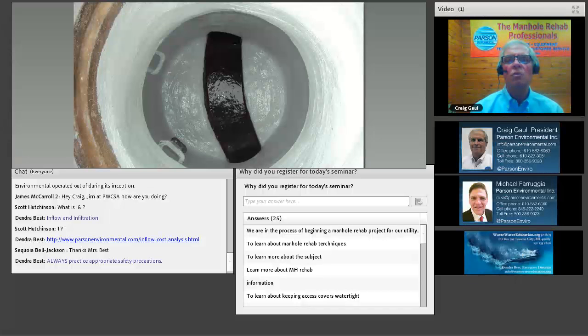The newest product on the line, and there are a few companies that have them now, is called a geopolymer material. It looks just like a cement product. It acts like a cement product. It smells like a cement product. But actually, the main ingredient, which in the MH Liner's case is Portland cement, is replaced with fly ash. And it's been found that fly ash really provides some great corrosion protection, because it takes the cement matrix out of that complete formula, and the cement is what gets attacked by hydrogen sulfide and MIC corrosion.